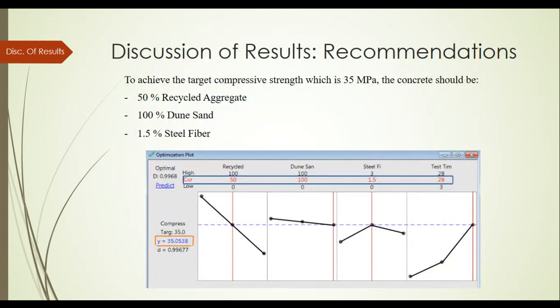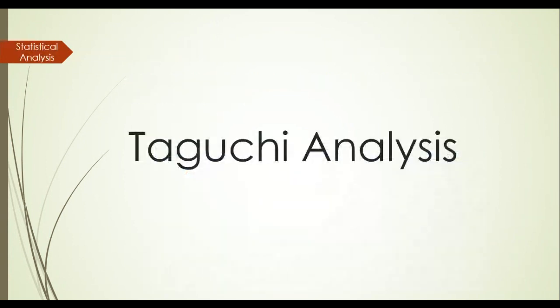Well, then based on that, the selection would be, for example, here 50% recycled aggregate, 100% dune sand, and 1.5. It will give you a yield strength of 35 megapascal as a compression test, compression strength. Okay, so these are the results that came out from the full factorial.